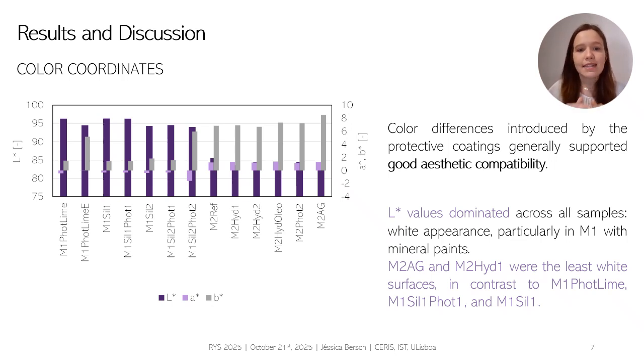What we can see is that L values dominated across all specimens. This is because we have a white appearance, particularly in M1 with mineral paints, which is expected since lime-based paints and silicate paints were white. In mortar 2, the anti-graffiti coating and the hydrophobic one showed the least white surfaces, that is, with the lowest L values.